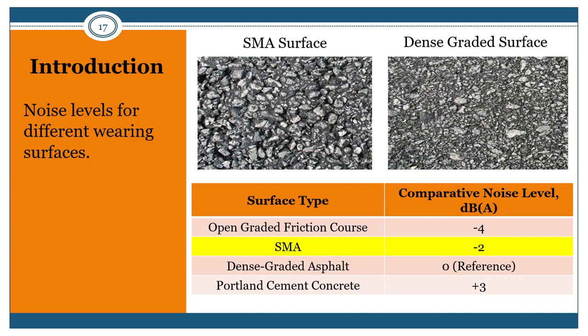Another advantage of SMA mixtures is noise reduction in comparison to conventional dense graded mixtures. As shown in this slide, the dense graded asphalt mixture noise level is included as the reference. So the difference in the decibel level is considered 0. The Portland cement concrete surface is noisier, with a noise level that is higher by 3 decibels on average. Conversely, the SMA mixtures, as shown in the highlighted row, have a 2 decibel lower noise level in comparison to the dense graded asphalt mixture.